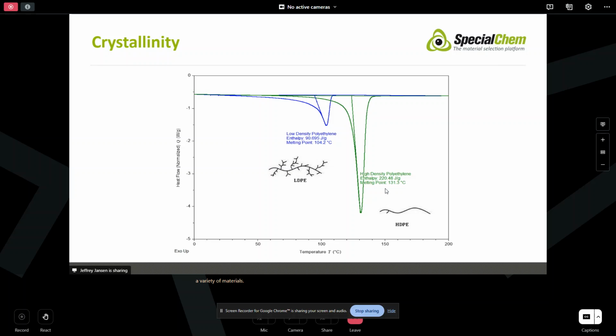So here's a great example of variation in that, and that's the relatively large difference between high-density polyethylene and low-density polyethylene. For one thing, high-density polyethylene has a much higher melting point, but you'll also see, depending on the grade, it's going to have a much higher heat of fusion. Here, 220 versus around 91 for this grade of low-density polyethylene. So again, differentiating our materials, where FTIR is not going to be a great way to tell these apart. DSC is going to tell us which we have and also give us insight into the crystallinity.